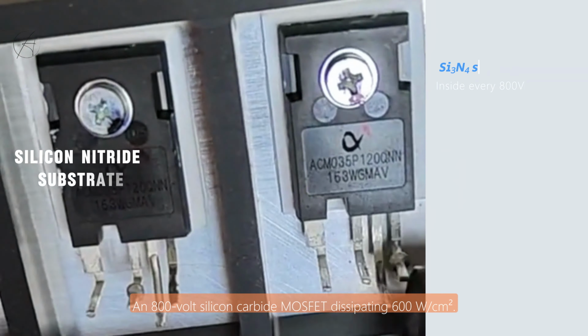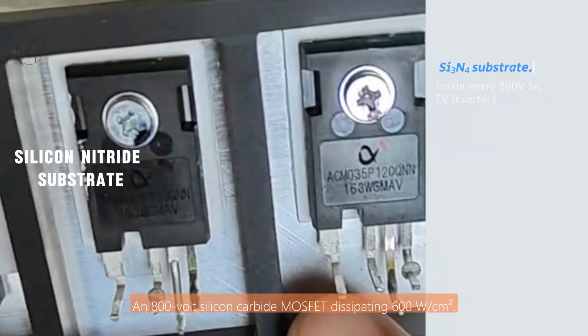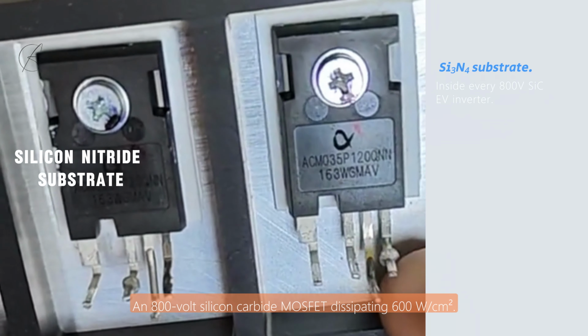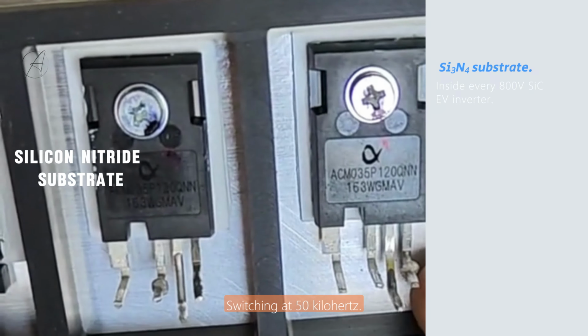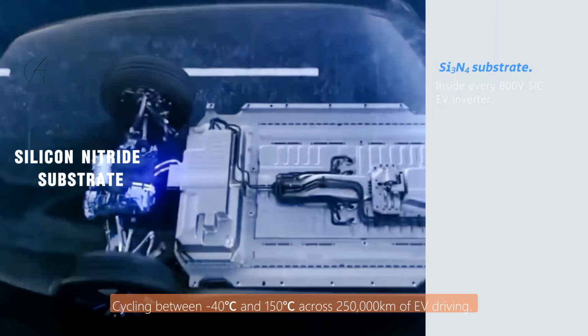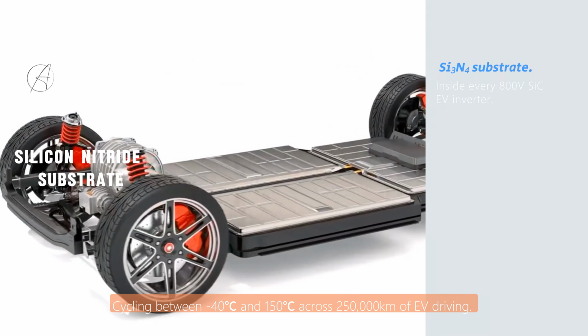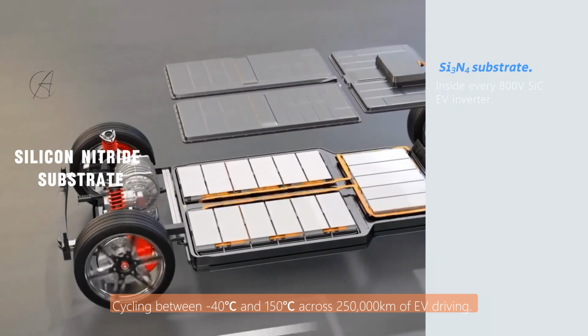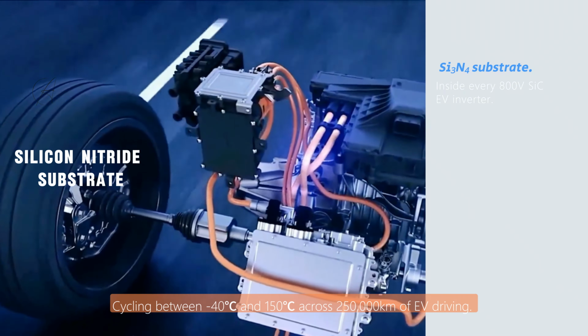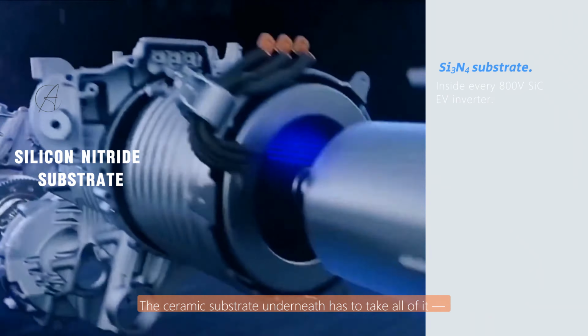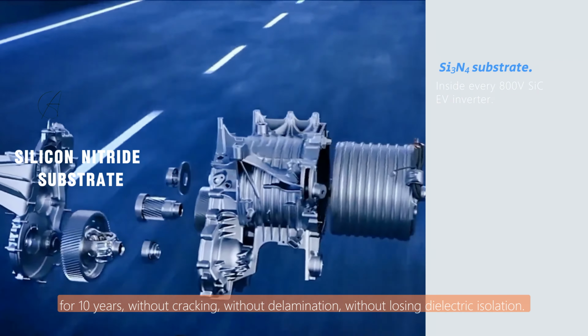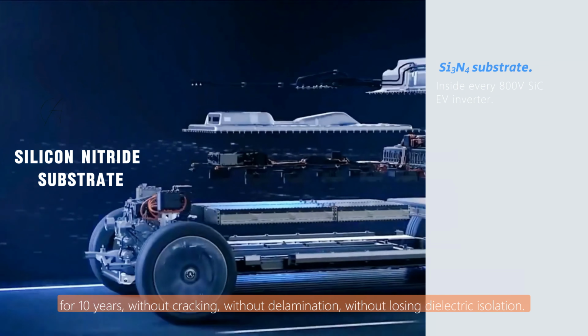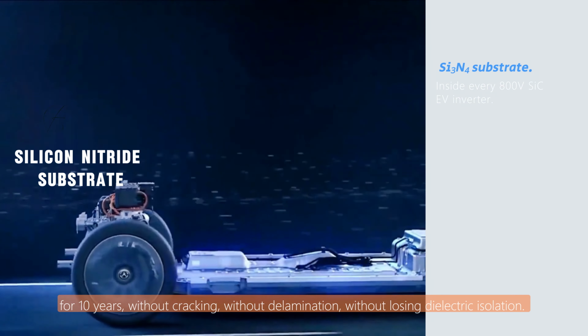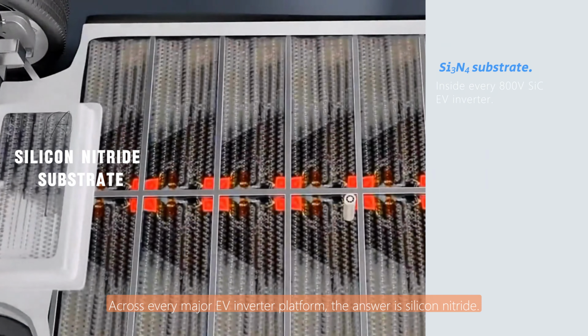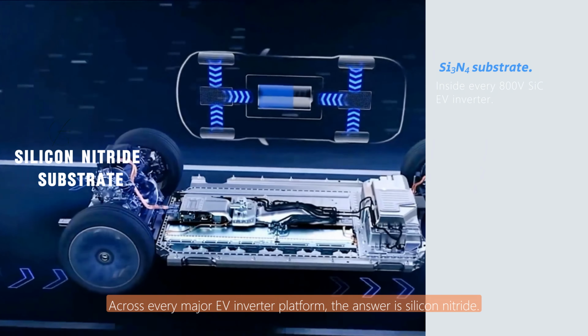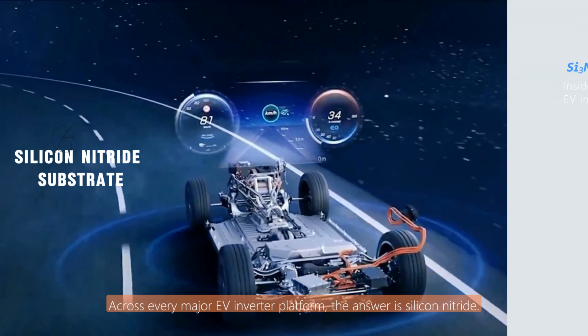An 800-volt silicon carbide MOSFET dissipating 600 watts per square centimeter. Switching at 50 kHz. Cycling between -40 and +150 degrees Celsius across 250,000 kilometers of EV driving. The ceramic substrate underneath has to take all of it. For 10 years, without cracking, without delamination, without losing dielectric isolation. Across every major EV inverter platform, the answer is silicon nitride.